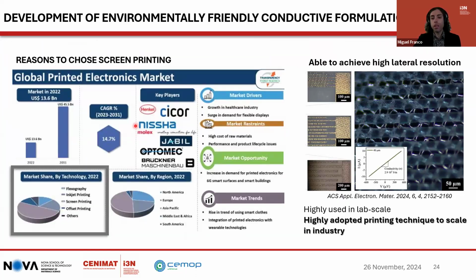Why use screen printing for sensor fabrication? First, it is the most adopted printing technique in the industry, and it can achieve a high resolution, up to 20 micrometers if using stainless steel meshes.